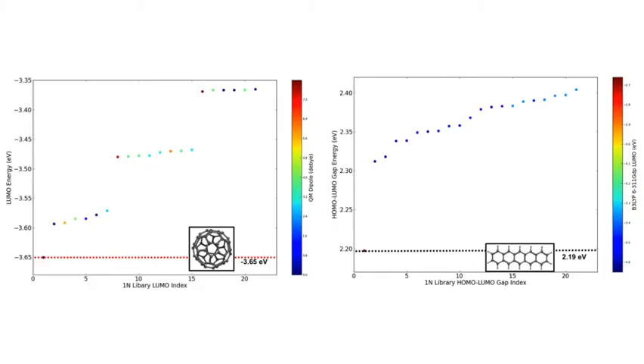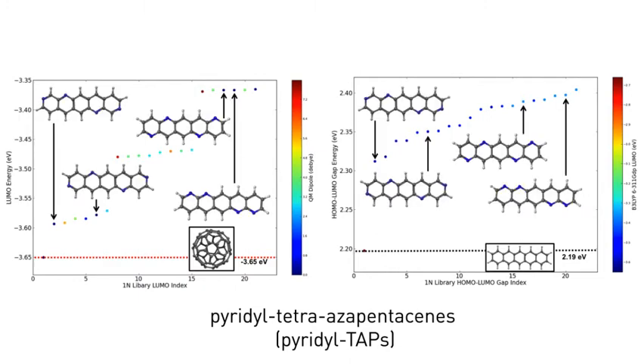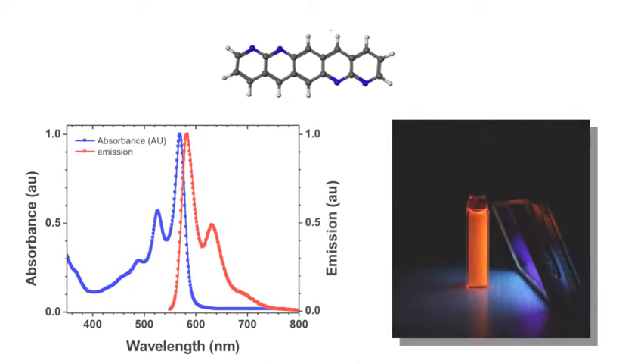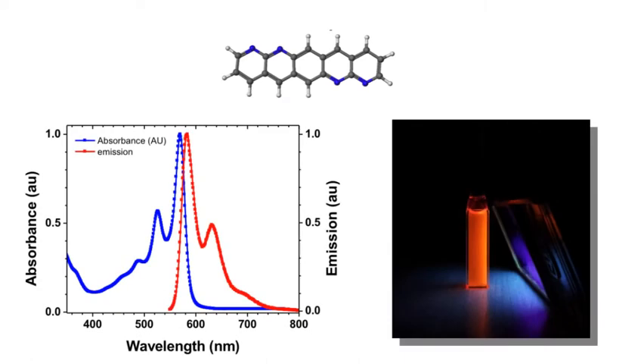Revisiting the graphs, we highlight another subset of only the relatively inexpensive and more synthetically tractable pyridyl tetraazapentacenes—those with one nitrogen per ring—and structures with zero dipole moments to minimize solid state trapping defines these exemplary structures. This one in particular has already undergone synthesis and experimental testing.